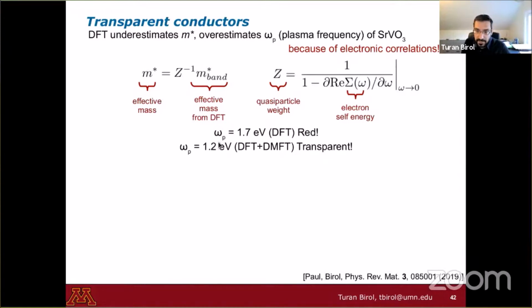Now, if you believe DFT, the plasma frequency of strontium vanadate is 1.7 electron volts. So it should be a red solid. It should reflect all red light. But if you take into account this Z, this quasi-particle weight as well, since the electrons behave more heavily, this plasma frequency goes down. It becomes harder to oscillate them. And the plasma frequency is suppressed to 1.2 eV, which makes it a transparent metal. So it reflects infrared light, but not visible light.